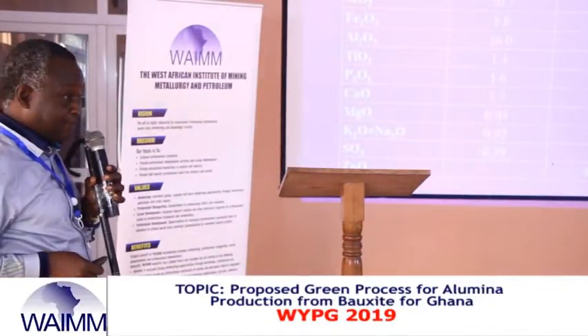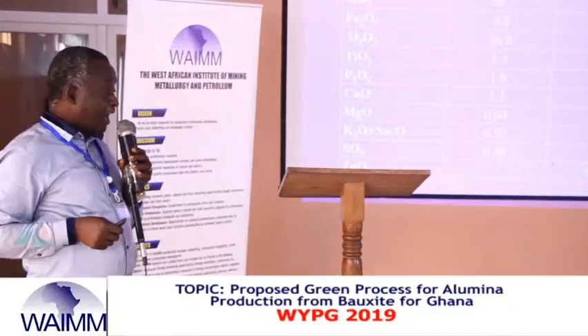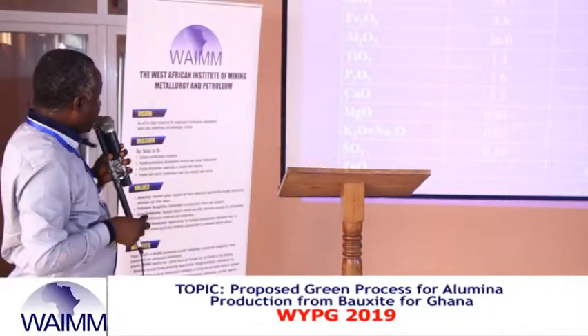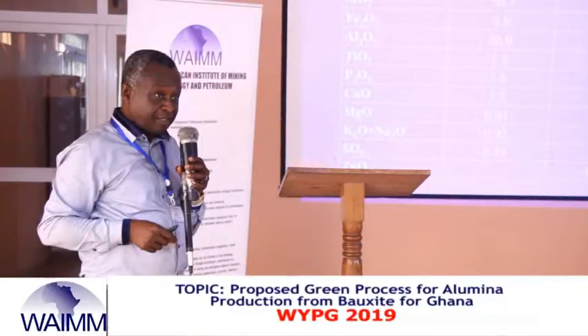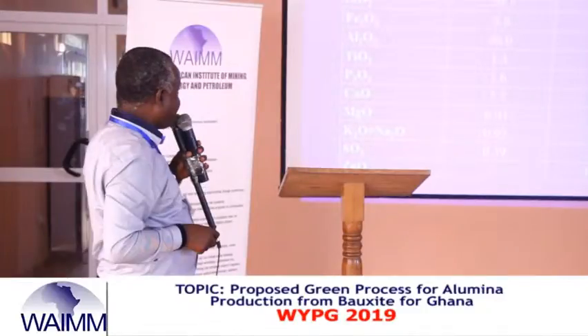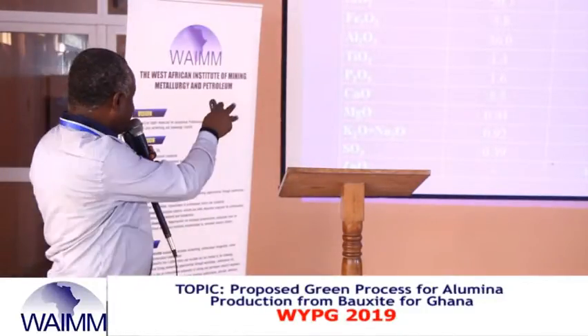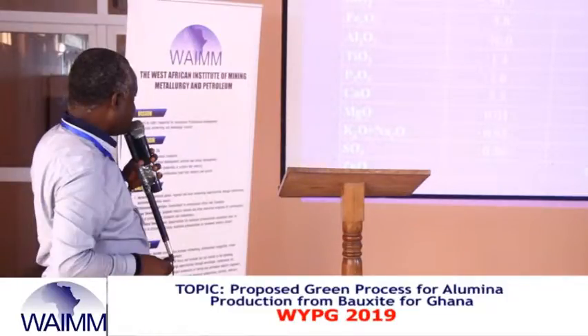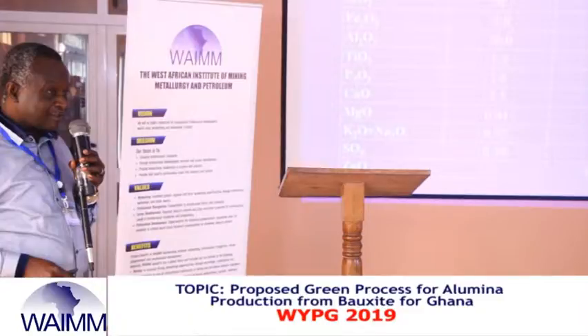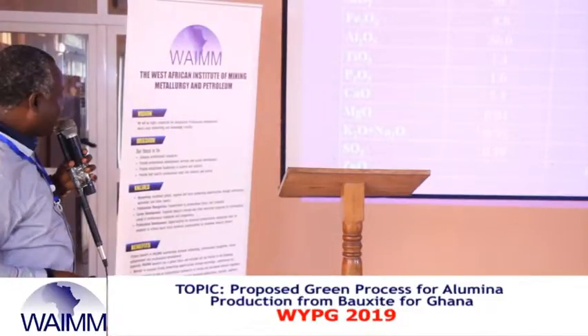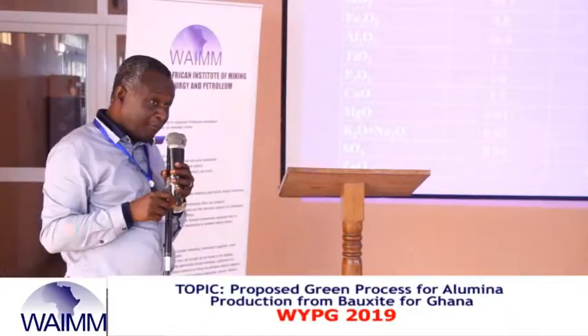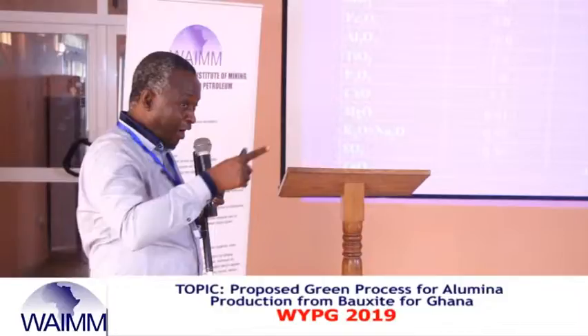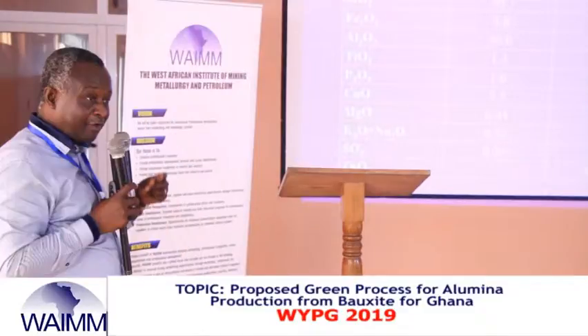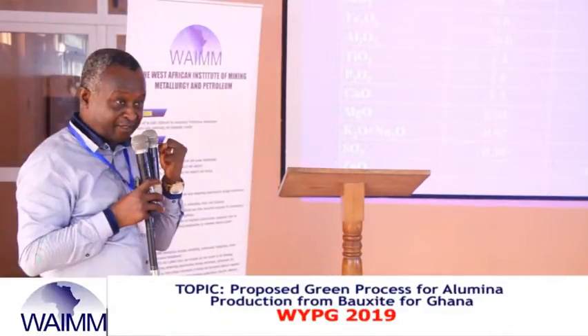We did some ash analysis, and for the ash analysis, you compare rubber tire to metallurgical coke that is used in the industry. You see that silica is only 27.94 for rubber tire, as opposed to 50.7 for metallurgical coke. And then we have a few others. Now, once again, check SO3. What do you notice? You see that the SO3 for metallurgical coke is only 0.39, but the rubber tire is once again 7.58. This will end up in the metal. We saw something curious, zinc oxide in the ash of rubber tire that could go up to about 40.81. So we notice that when we get to the point where we are using it industrially, that could also be a potential source for getting zinc for the commercial production of zinc as well.